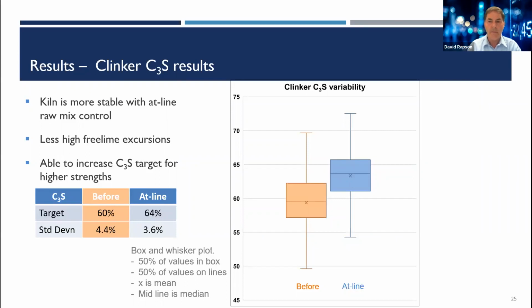So this is the same clinker data as the previous slide, just presented a little bit differently. There's a box and whisker plot here. What this is showing is that 50% of the values are inside the box. Another 50% of the values are outside of the box, shown by the 2 lines. X is the mean and the line through the box is the median. So here the blue box is smaller than the orange one, confirming that there's reduced variability.